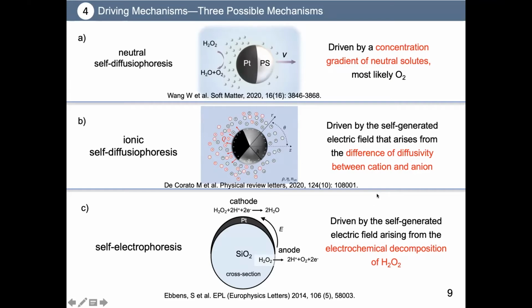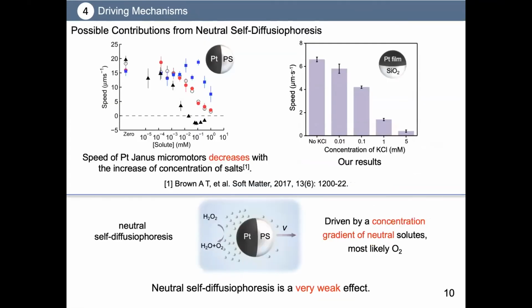Recently, people discovered the speed of platinum Janus micromotors is sensitive to the ionic strength of solution. Our experimental results found that the speed of platinum Janus micromotors decreases with the increase of concentration of salts. So that indicates that the neutral self-diffusiophoresis is a very weak effect.